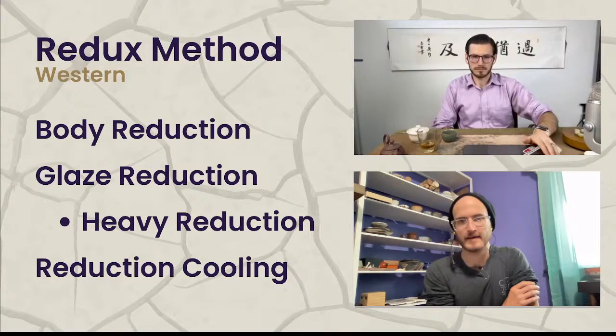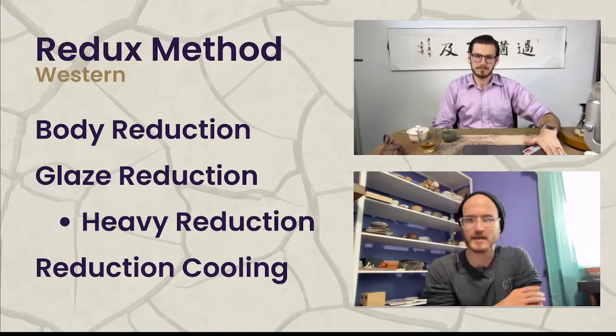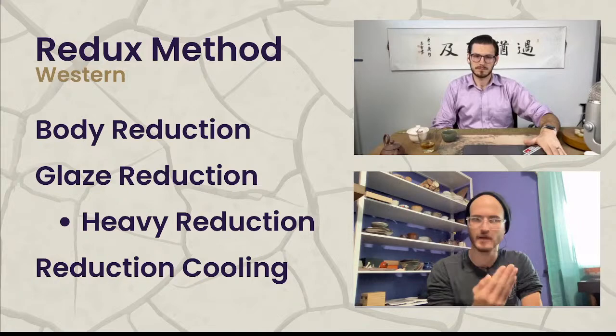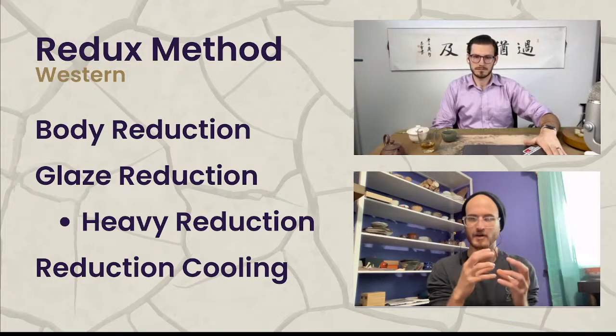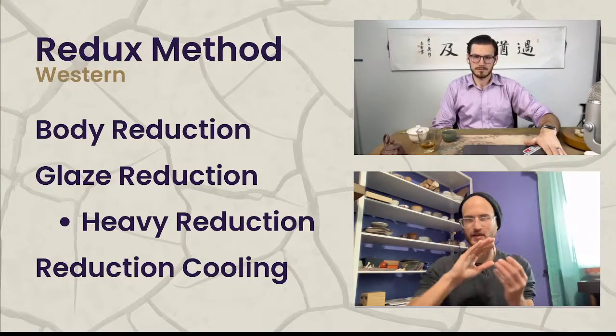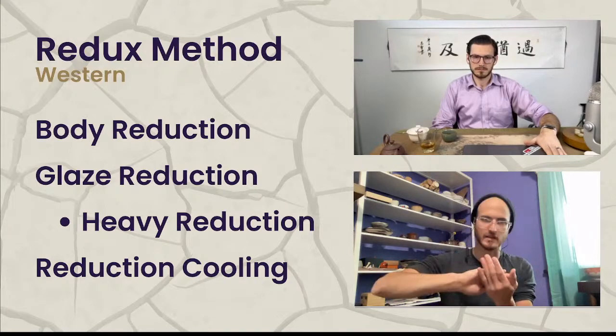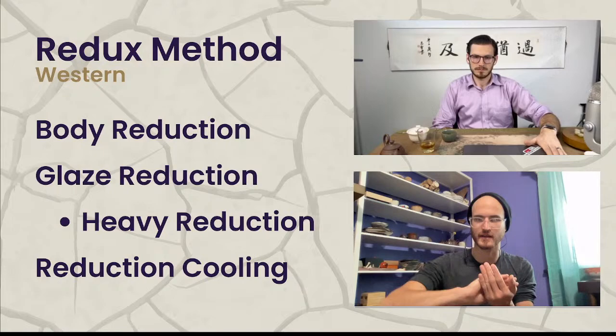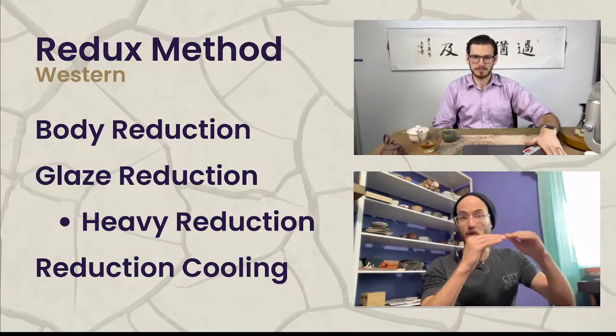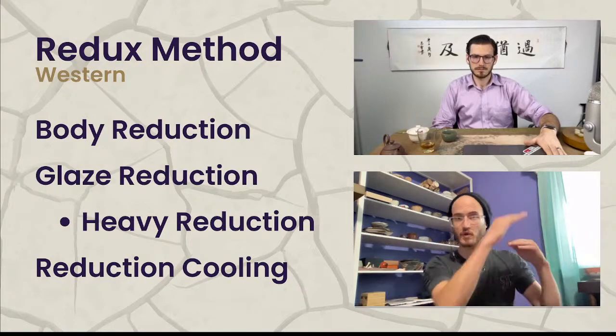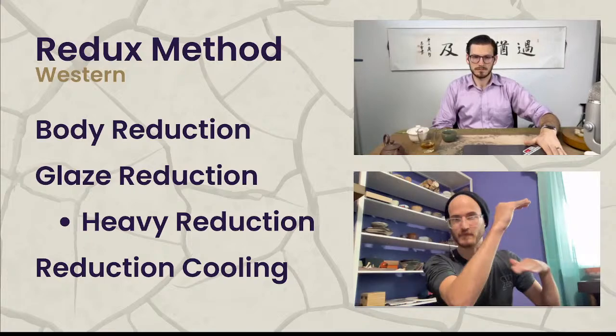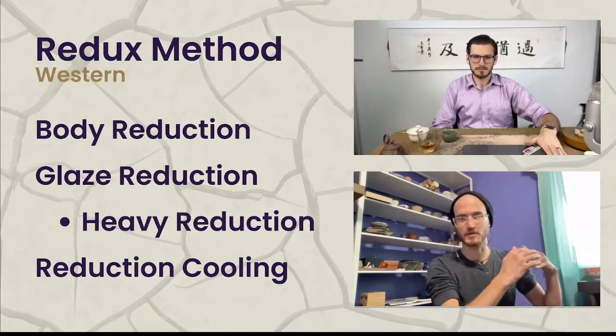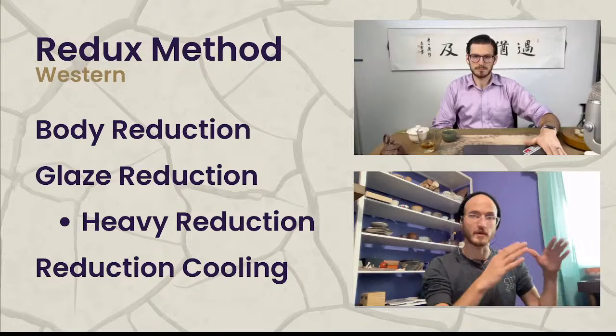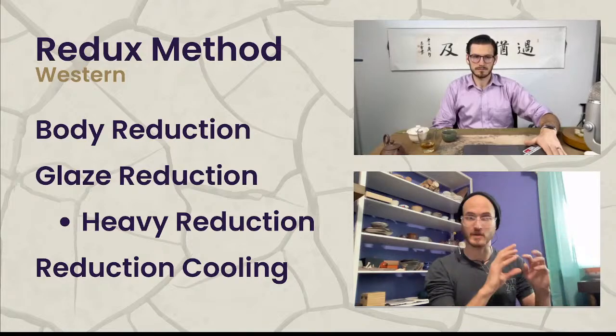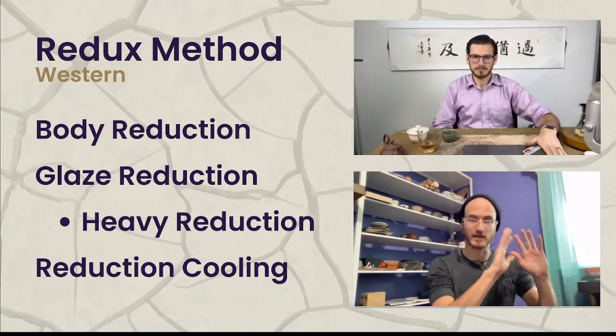But that's the idea, is that you're sort of sealing off the color when you drop that temperature, and you're giving it just that last little bit of interaction with the fire, and it allows the surface to sort of seal off and become a little bit more matte, and then it'll cool slowly after that point. So you only crash it down, 50 to 100 degrees C usually is what you're going to do. And then you let it cool slowly from that point forward. And that means that you can still get crystalline mattes. You can get crystalline glazed surfaces because that can still